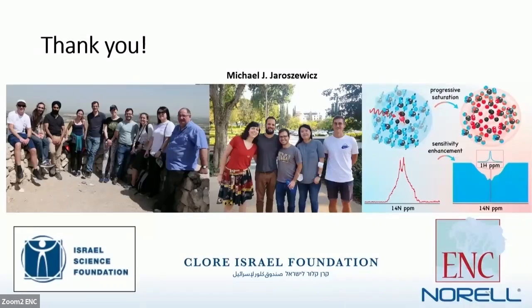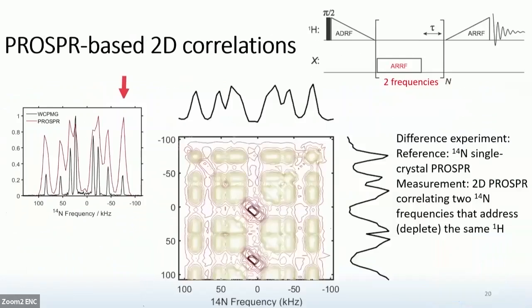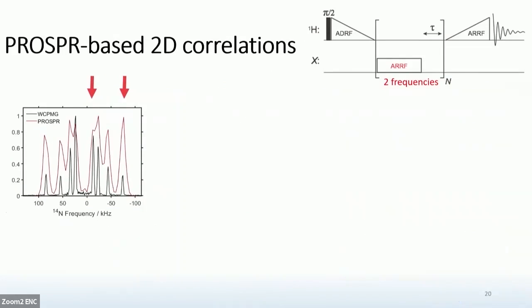Yeah, that's a good question. So T1D essentially would be the equivalent of T1, but it's the time scale that determines how long your dipolar order lives. The way I would measure it is similar to a saturation recovery, but I would generate the dipolar order, then gradually increase tau, and then I would remagnetize and measure it again and see how much is left. So the decay would look similar to a T2 decay, depending on your different delays. And that's how I would measure it.